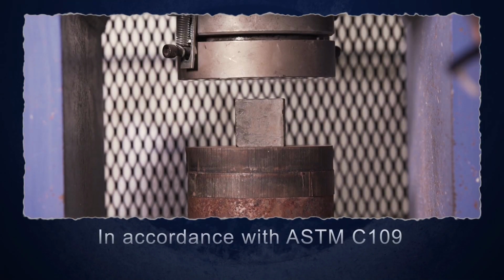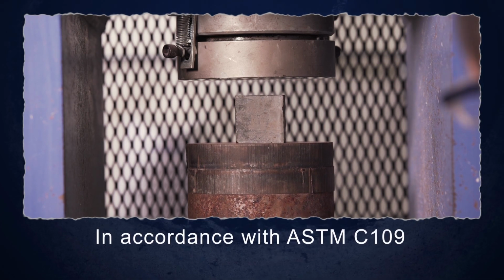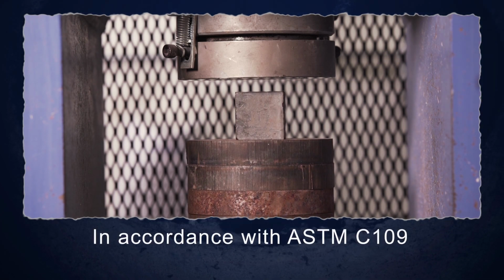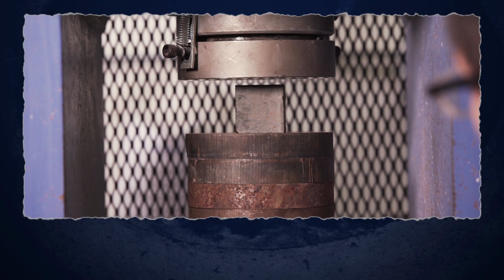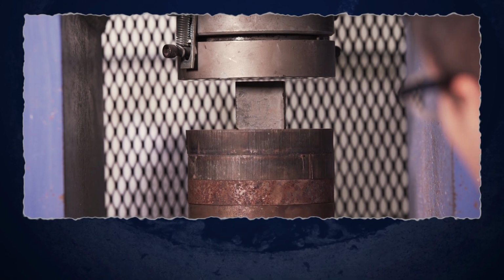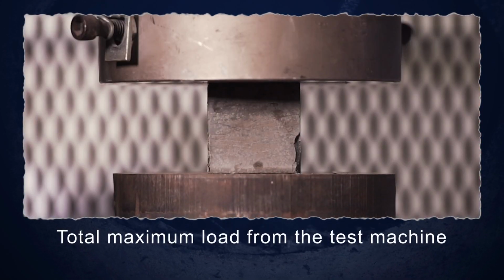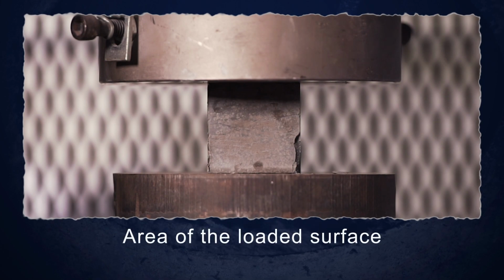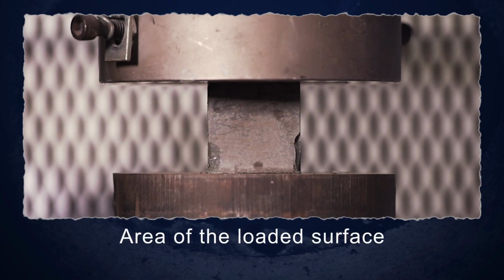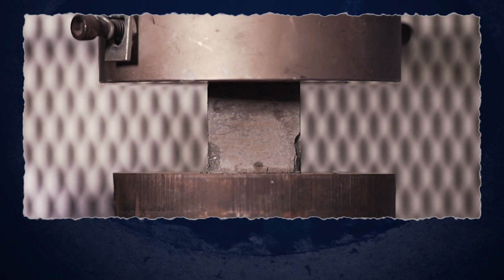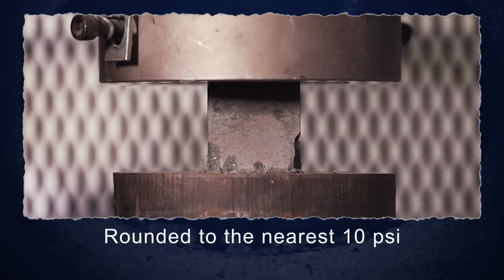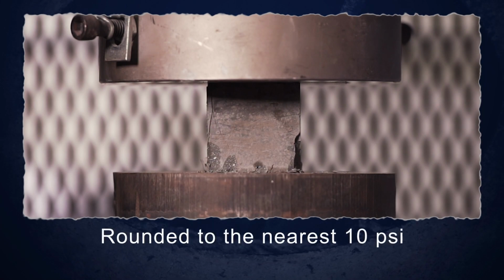Utilize procedures and load rates in accordance with ASTM C109 to load test the cubes to failure. Compressive strength is determined by dividing the total maximum load from the test machine by the area of the loaded surface. Average compression strength for each set of grout specimens should be rounded to the nearest 10 psi.